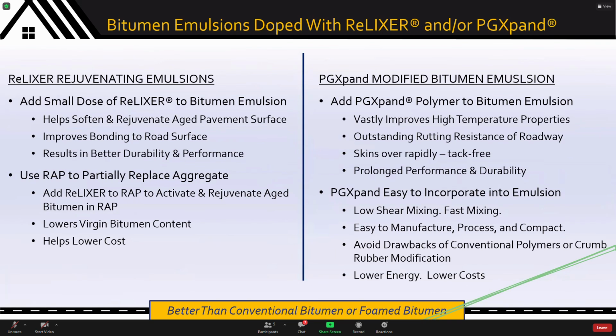Both ReLIXER and PGXpand are also used in emulsions for chip seals, for microsurfacings, for slurry seals, for fog seals. In the case of both, very easy to use. In the case of ReLIXER, with or without RAP, adding a little bit of ReLIXER to the bitumen emulsion certainly helps soften and rejuvenate the aged pavement surface, so it is better able to accept and bond with the fresh surface being put down.